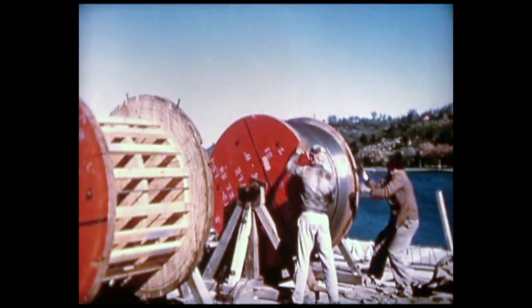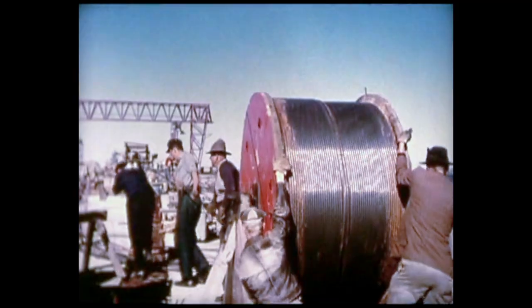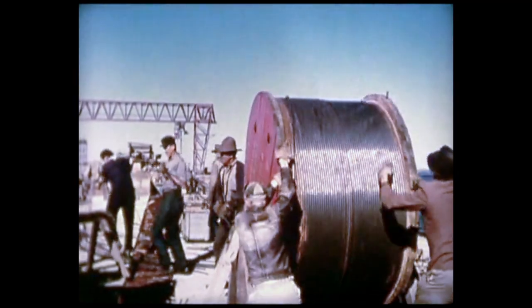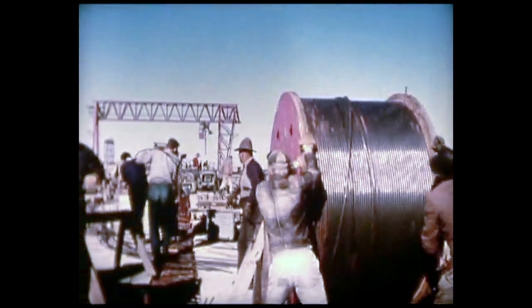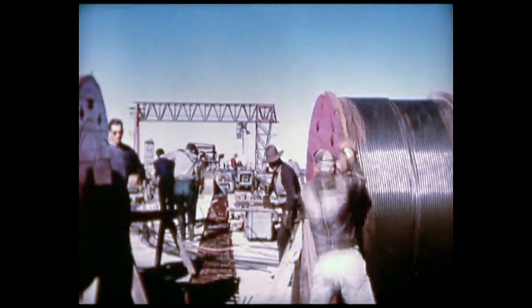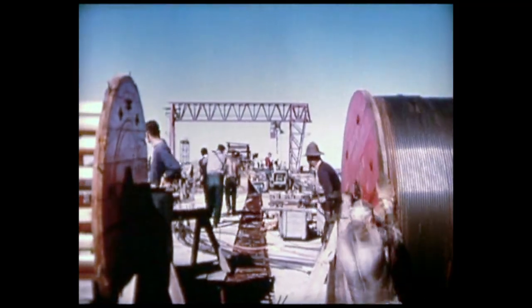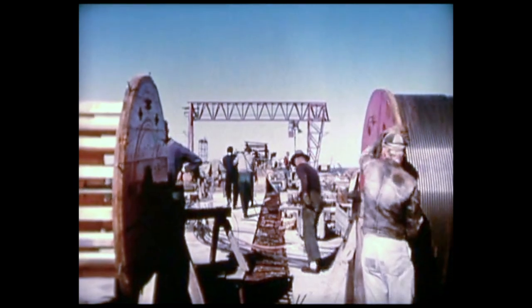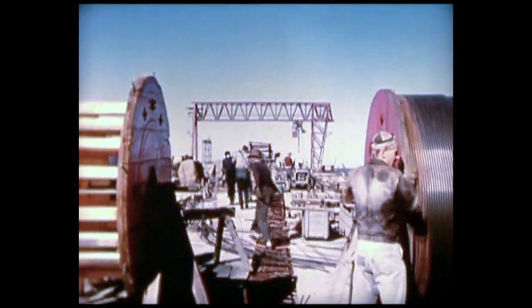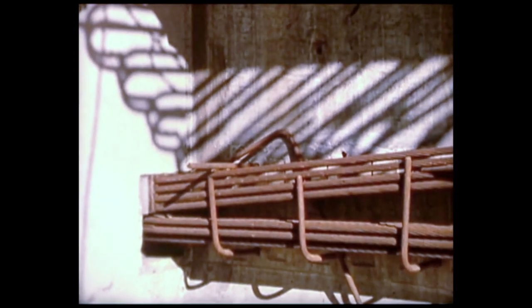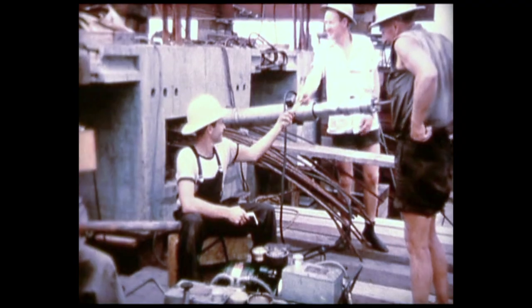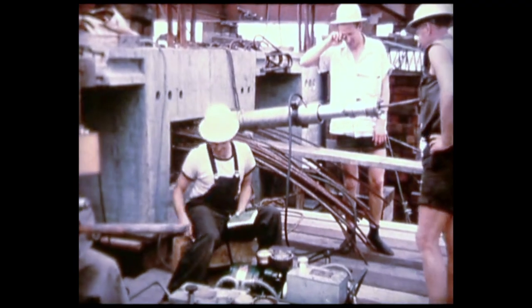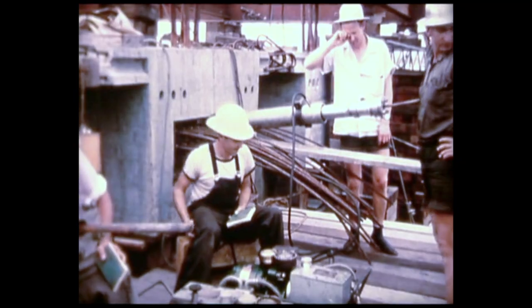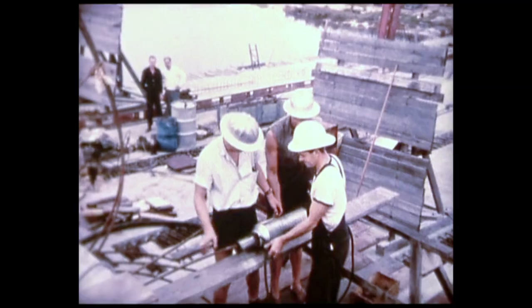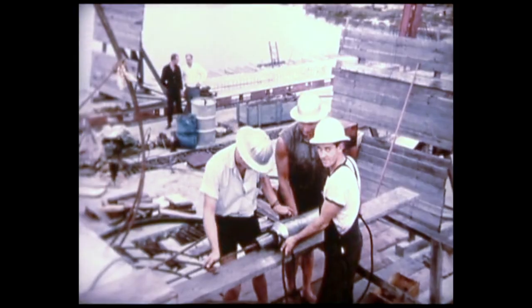And now the tensioning. Tests made on stranded wire ropes led to the development for this structure of a rope of 0.7-inch diameter comprising 19 wires, which is used with a split wedge anchor. Lengths of wire rope were fed along the assembled section. The groups of wire ropes imposing the longitudinal pre-stressing force were placed outside the web. The tensioning force was applied at each end of the rope, and when the required force was reached, it was secured by split wedge anchor grips.